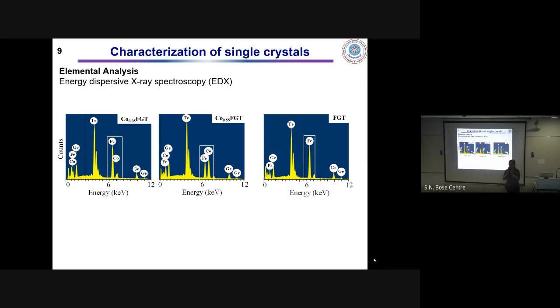Not only that, our main motive was, before doping, we were first interested in observing the unconventional transport behavior of Fe3GeTe2. So the gradation of the work was like this. We started with Fe3GeTe2 first, and we confirmed that we can observe skyrmion-like spin textures in our system. That entire part was done. Then we started to see what will happen if we tune the iron concentration. While tuning, the easiest way is to look at the nearest atom. We know that in this compound the iron is not exactly 3.